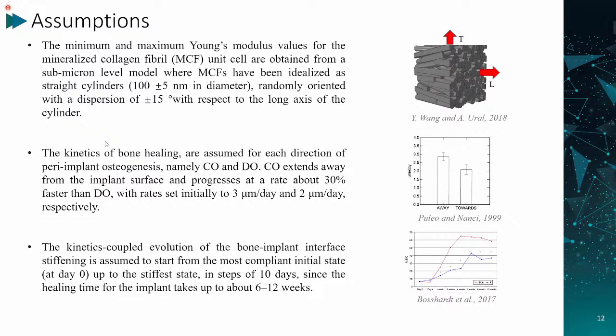A second assumption: the kinetics of bone healing are assumed for each direction of the peri-implant osteogenesis, the CO and DO. So CO extends away from the implant surface and progresses at a rate about 30% faster than the DO, with rates set initially to 3 micron per day and 2 micron per day, respectively, which means CO goes from the implant to the old bone.